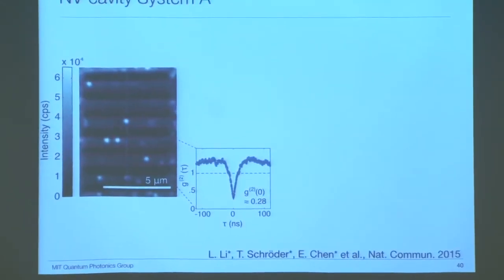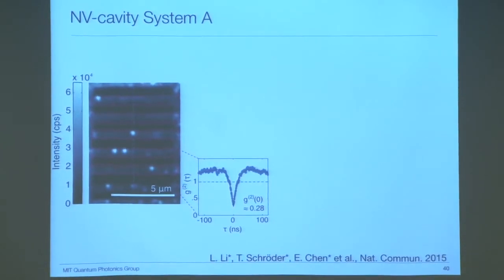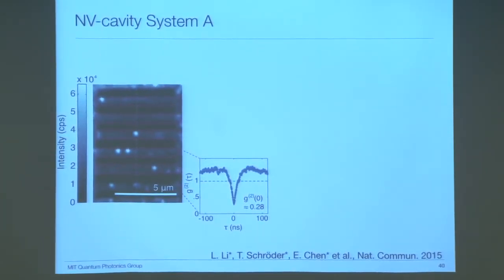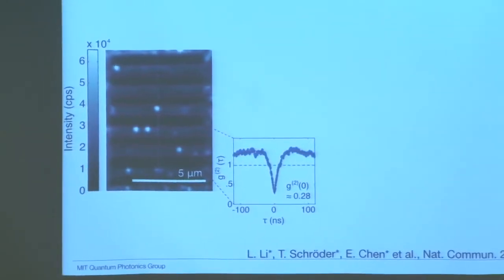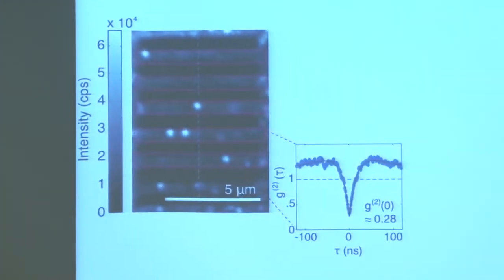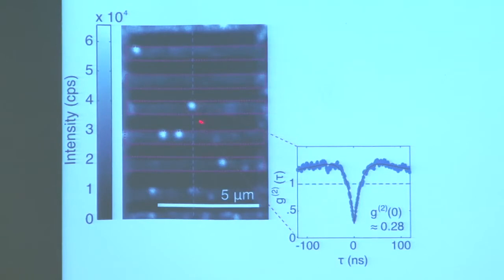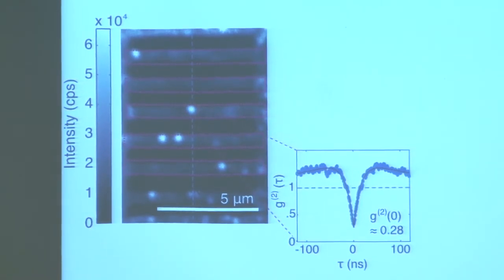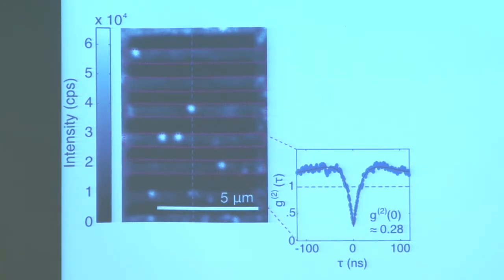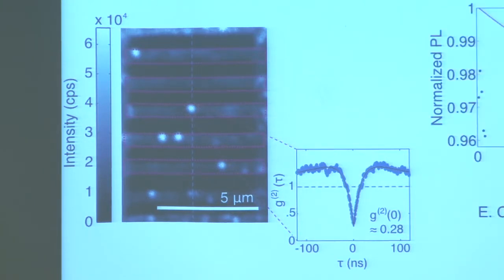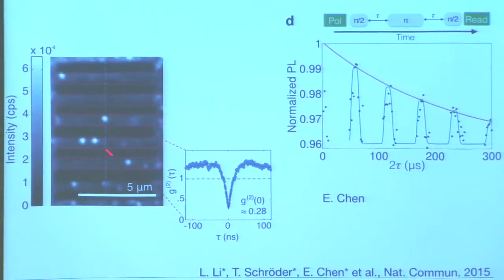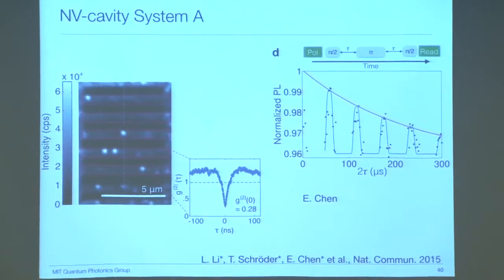Here is a scanning confocal microscope image of a diamond sample. We can see these cavities as red dotted streets. And we also have NV centers as bright spots. And these NV centers are confirmed to be single photon emitters by second order autocorrelation measurement. And these NV centers are randomly distributed inside of the diamond membrane. Sometimes we get lucky, we find this NV cavity system A, which has a bright NV center inside of a photonic crystal cavity.